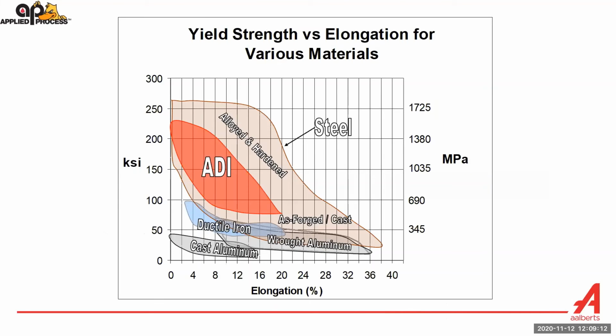This is a powerful chart. This plots for various materials yield strength versus percent elongation. And the pink zone on here is alloyed and hardened steels. The blue zone is ductile iron. Notice they don't overlap a lot.